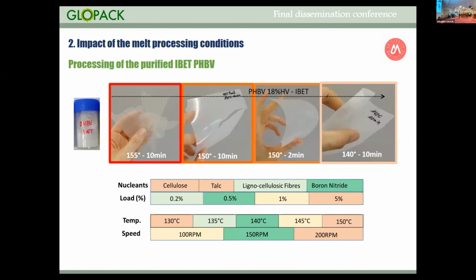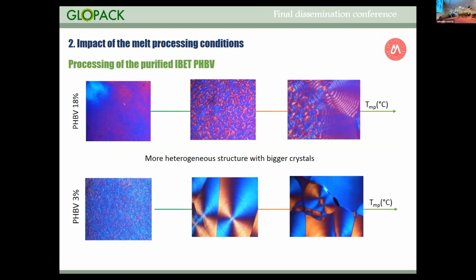And how did we have such important differences in mechanical properties? We also did an in-depth study of these materials, and you can see that depending on the processing temperature, the microstructure is completely changing from a homogeneous structure to big crystals and so on. And as you can remember, if you have big crystals, you have more brittle materials.